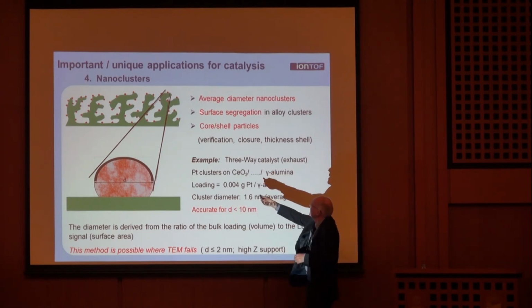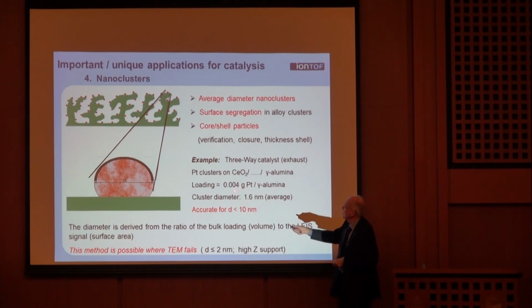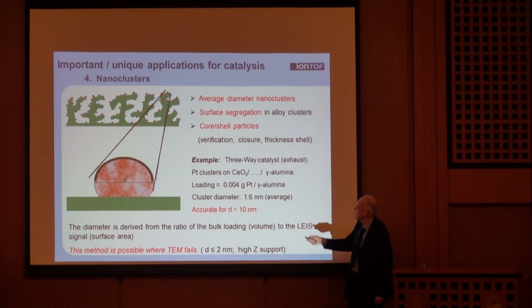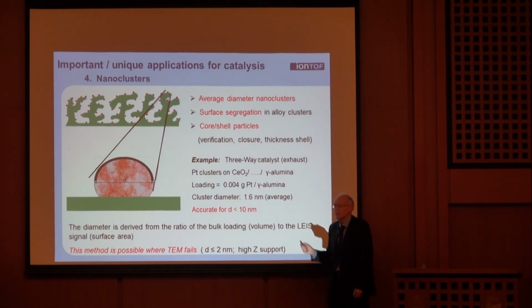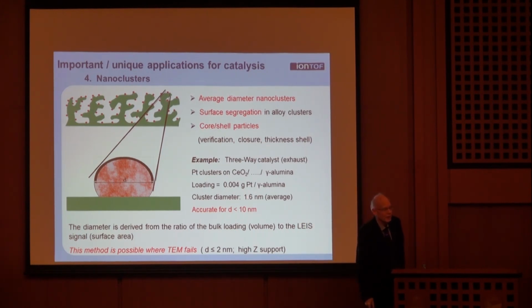And so in this case, we looked at a real three-way catalyst with a normal loading of so much platinum on gamma alumina, and we determined that the diameter of this cluster is 1.6 nanometer. That is reproducible and accurate. Especially for small clusters, it's easy to measure because there's more surface area. It's easier.